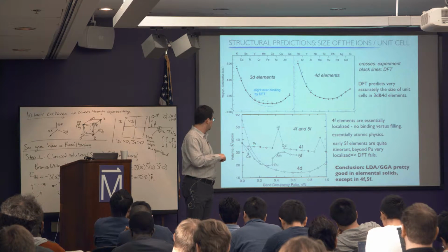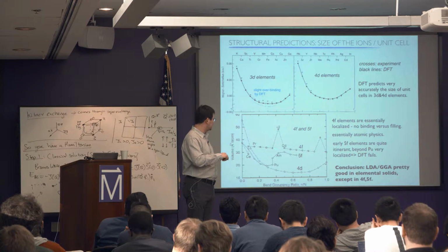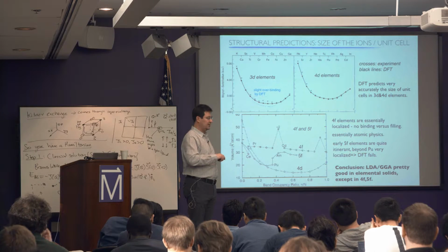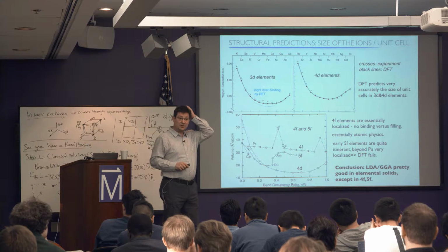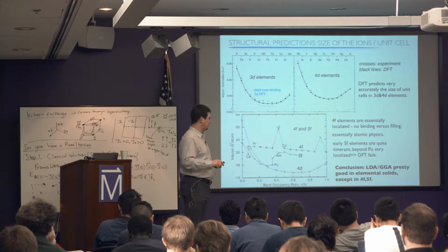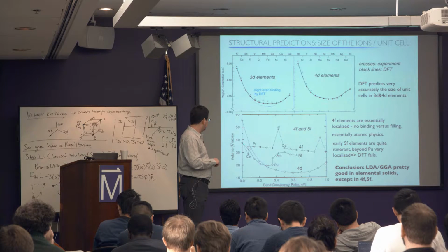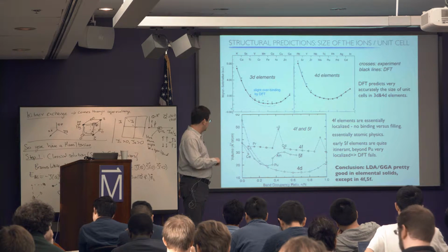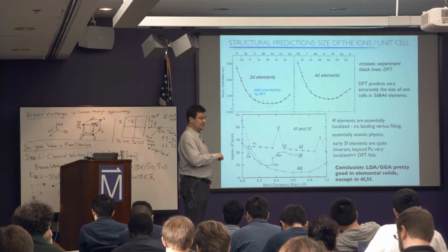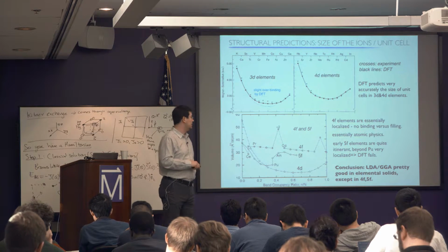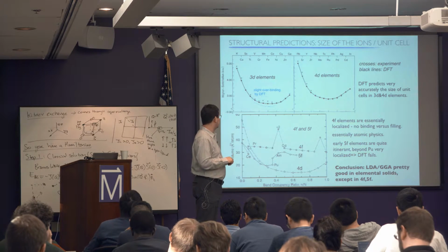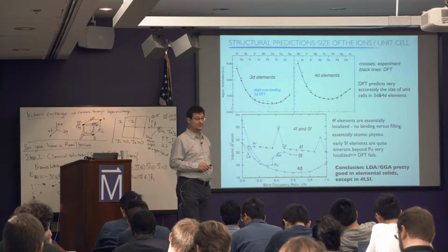But in lanthanides, you see that this curve is flat, except there are some peaks in particular valencies where you have very strong multiplet effects. Okay, so this you cannot predict at all with DFT. This is very bad. Now in actinides, however, there is reasonable agreement with DFT for this part, this down term, but then around plutonium it jumps, and here you have more or less localized behavior. So in f systems, DFT has difficulty explaining, but at least in 3d and 4d it's pretty good.